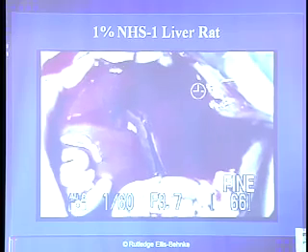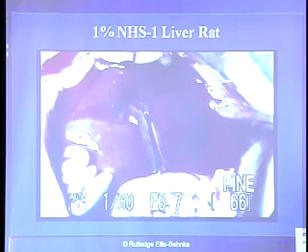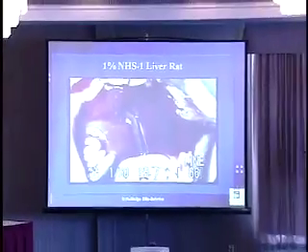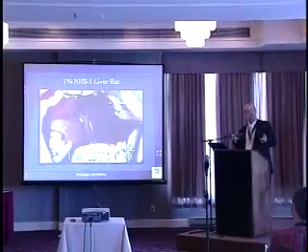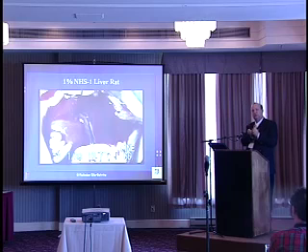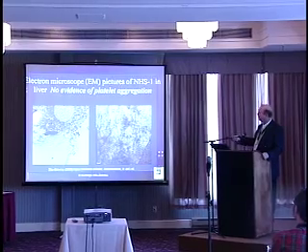And we've gone to other types of ways to do this, and this comes back to something we saw earlier today: the modulus of the material you put in. If you have something of the wrong modulus, it shears apart. That's in one of my papers. If the modulus is too stiff, it pulls apart. It has to match the tissue, otherwise it won't work properly. I won't go through this one because it's a little bit long, but it's just a bigger bleeder.